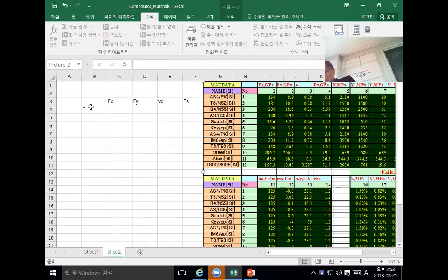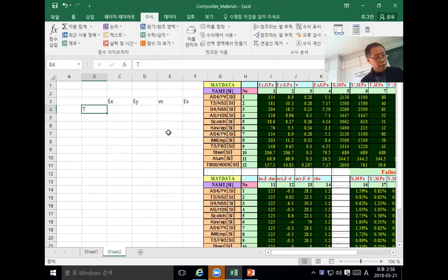So let's say just use a T300 epoxy and T700 epoxy, just T300. Well, these happen to have very high stiffness, 181 and 10.3, and Poisson's ratio is 0.28.